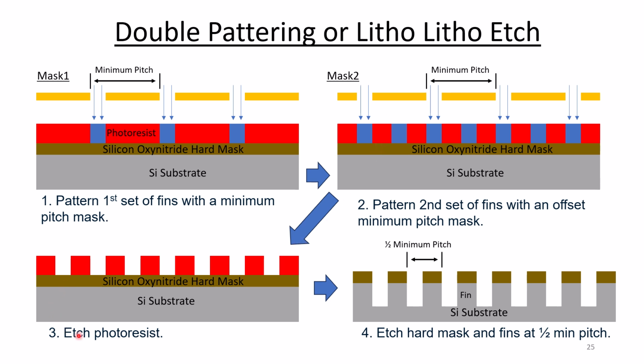Now for the third step, we come in here and we etch our developed photoresist, and it leaves a pattern behind. And now we use that pattern to etch the hard mask, and then we use the hard mask as a mask to go ahead and do our anisotropic etch for the fins. And what this does is it gives you 1/2 the minimum pitch. Now it required using 2 masks, one at a minimum pitch and a second one at minimum pitch, but then just offsetting the process slightly to expose something that gives you 1/2 the minimum pitch.